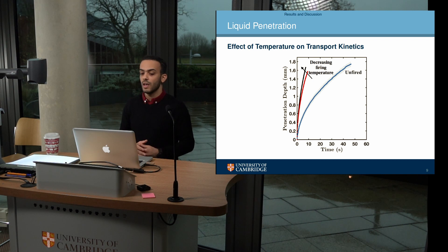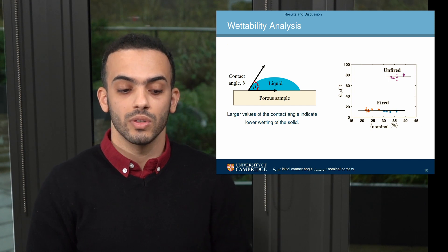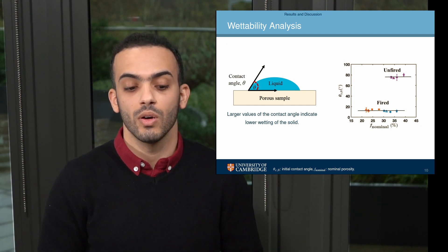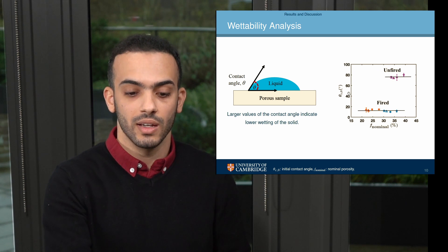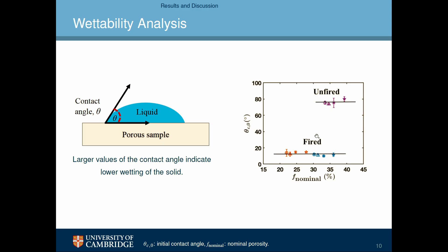In order to further investigate this, contact angle measurements were conducted to measure the wettability of the samples by water. Looking at the results of the initial contact angle of the different alumina samples — unfired and fired — where the same color represents a specific heat treatment condition and each line represents a specific compaction condition, we see that the unfired samples have larger contact angle values compared to the fired samples at the same compaction force, indicating that the unfired samples have lower wettability and hence a lower rate of liquid transport. This confirms the observations in the terahertz results.